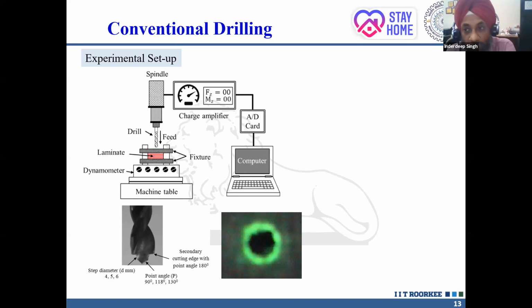And that was a good contribution in the field of research, because prior to that most of the researchers, not only in India but globally, were trying to analyze the holes just by visual inspection only. So their assessment of the damage around the hole was more or less qualitative, but we were able to develop a very simple process which was far more accurate as compared to the qualitative assessment by visual examination. So it was appreciated also, and we were able to publish that work also.